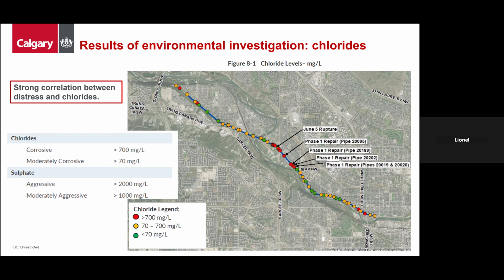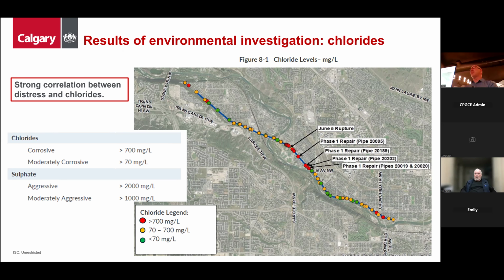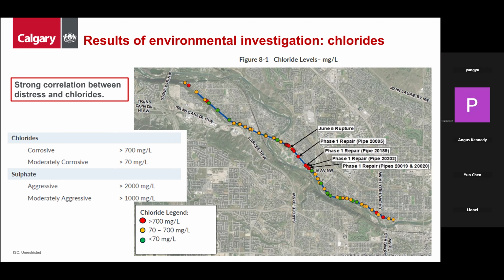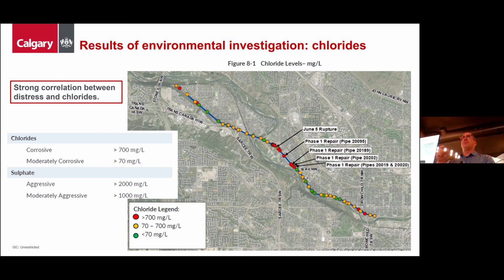In fact, the 5 hotspots were well in excess of the requirements that we had for the number of wire breaks that put the pipe at risk. We found quite literally hundreds of locations up and down from the break where we had identified that the pipe was in some form of distress. So quite literally, the pipe was riddled and continues to be in areas having structural deficiency. Ergo, the reason we've put in that monitoring system that I'll talk a little about here.